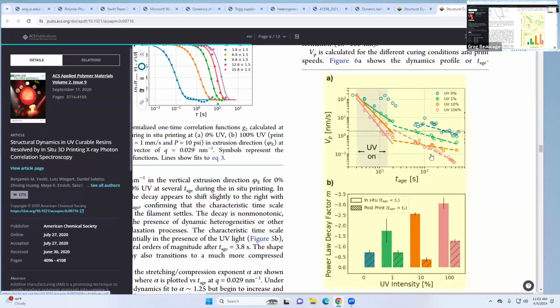But we kept that measurement on for several hundred seconds after we printed the filament, and we saw that the dynamics continued to evolve and still decay. When you're trying to 3D print something, you're trying to go as fast as you can, one layer, another layer, another layer, right? But from our experiments, we found that the structure and the dynamics are still evolving hundreds of seconds after you printed that layer. So you can't just print it and move on. It's still alive, it's still changing.